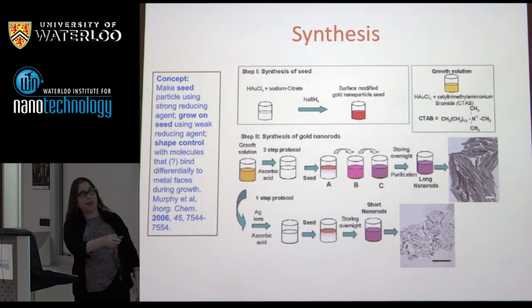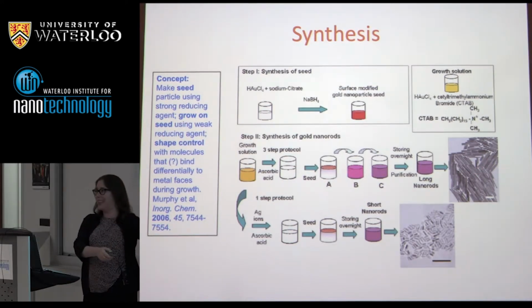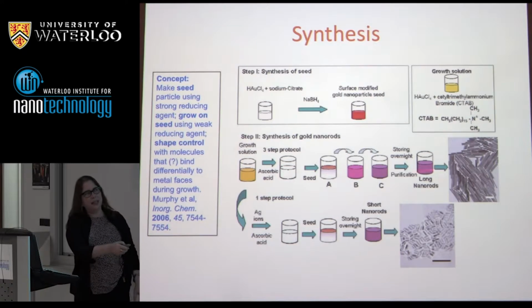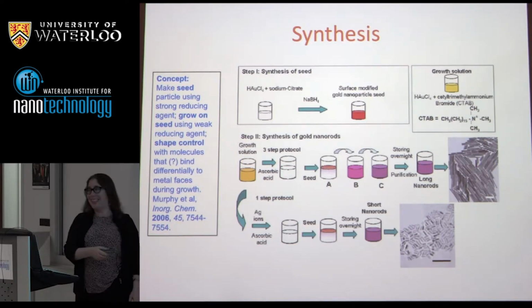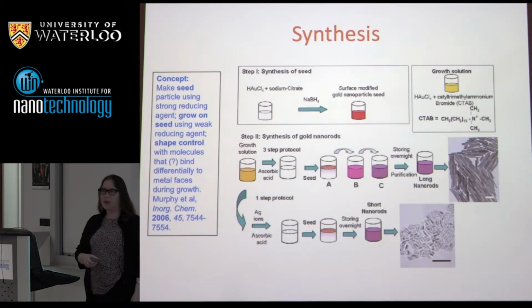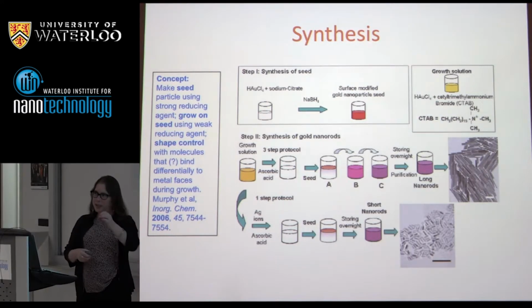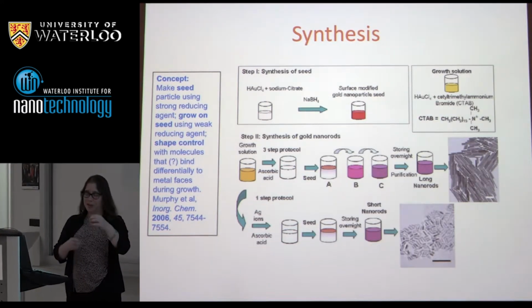And you can stop it along the way and get smaller aspect ratio materials. Silver, you can do this, it takes off and makes really long wires, but you kind of lose control over the length. This sounds great. What's the problem? The problem is yield. Yield is terrible. It turns out most particles do not elongate. Only a small proportion do, but of the proportion that do, they seem to keep going.